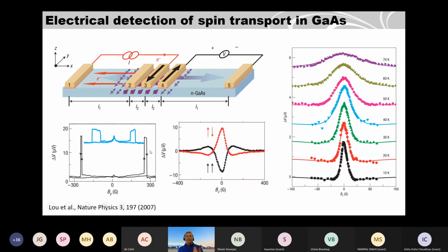Okay, and as I have shown you for the metallic spintronic devices, if you apply a magnetic field perpendicular to this, you create spin precession. So you see these Hanle effects for the parallel case, the black one, and for the anti-parallel case of the ferromagnets, the red one. And this is the temperature dependence of the signal. As you see, when you warm up, the line width of the Hanle curves is broadening. That means the narrower the line width, the higher the spin lifetime. So from this, you can find spin lifetimes of nanoseconds in this gallium arsenide.